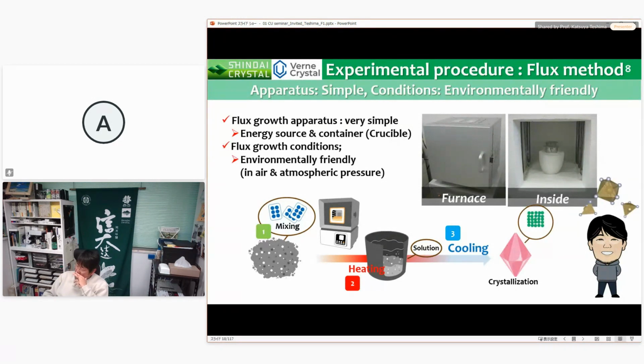This is the experimental procedure, simply three steps: mixing, heating, and cooling. First, raw materials such as solute and flux powders are mixed in air. Next, the mixed powders are put into crucibles, which are placed in an electronic furnace and heated at a given temperature for several hours. Finally, they are allowed to cool to room temperature, and the residual flux is dissolved in warm water to separate the grown crystals.